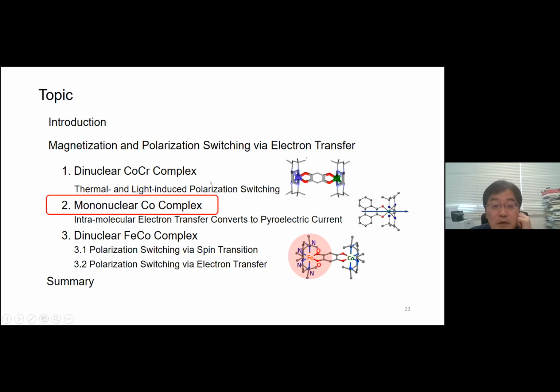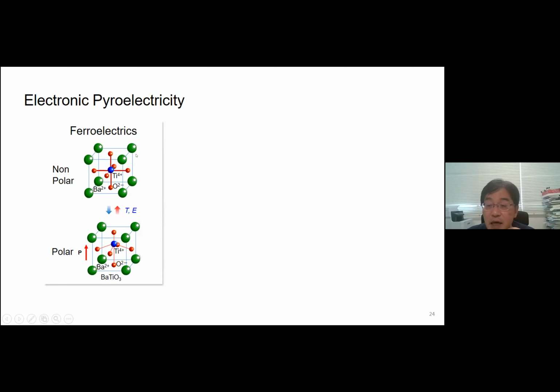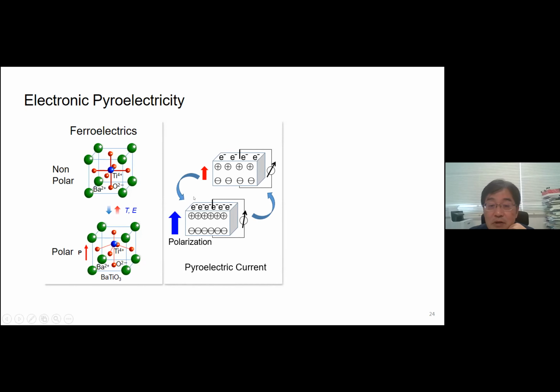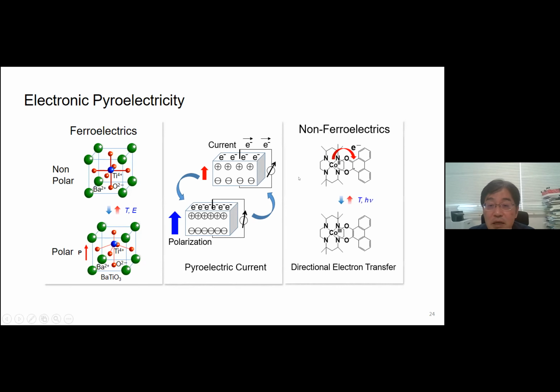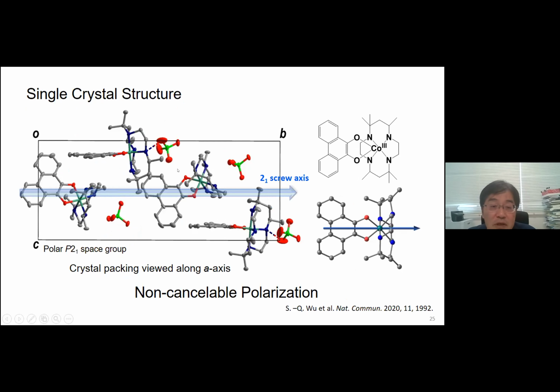And next, I'm going to talk about polarization switching of a cobalt complex and its pyroelectric property. Ferroelectric compounds have many interesting properties. One of them is pyroelectricity. Polarization change is detected by current. And in this study, we investigate the electron transfer-based pyroelectric current in this non-ferroelectric polarization switching material, this cobalt mononuclear complex. We synthesized this complex, and this is the single crystal structure. And this is a polar space group and the molecules are oriented in the same direction as shown here.